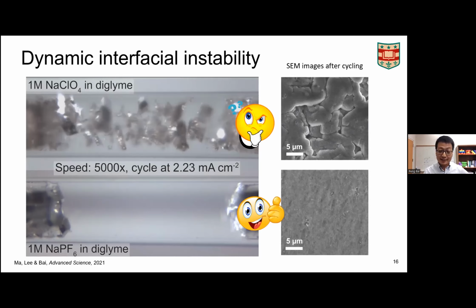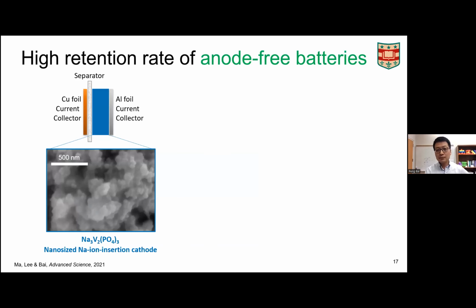So now it's really the time, because we showed the ideal deposition and the ideal reversibility, right? So we put that into a real anode-free battery. And remember that, as I said, you can remove the particles for the anode, right? But you still need to have the copper foil for the metal plating. You will still have the separator. You will still need the particles for the cathode. But still, you save nearly one half of the original volume, right?